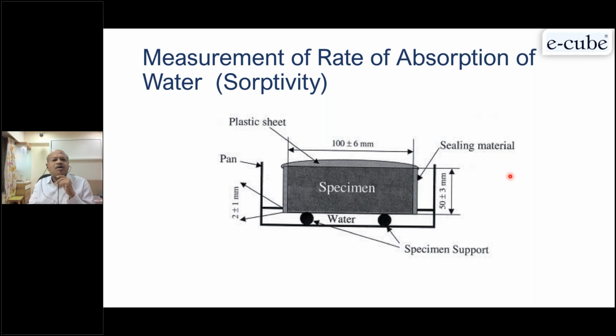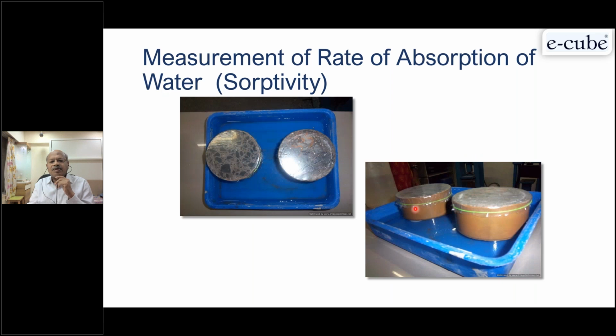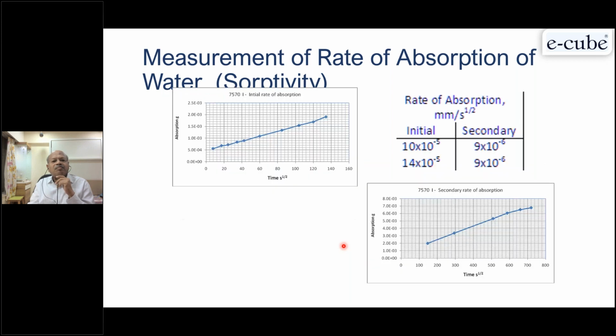And then water will absorb and you take the rate of absorption like this. This is the test we conducted in our lab. You can see this. And we can find out your initial rate of absorption and then secondary absorption. You can find out the rate, whatever specified. There is an ASTM for this, and you can use it.